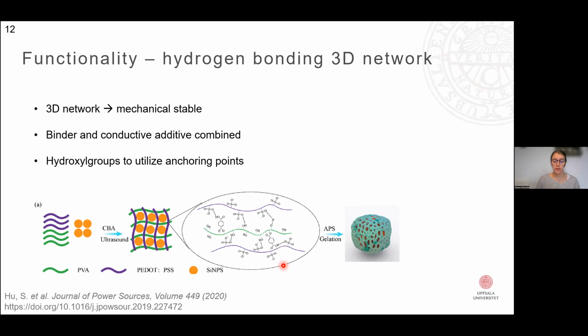Here's the difference. They also use hydrogen bonding, but in a 3D network, because they claim that it makes it more mechanically stable through the volume changes. So here they have a conductive self-healing hydrogel with a 3D network based on PEDOT:PSS coupled with PVA as the binder. And this network functions both as the binder and the conductive additive. And the authors mention here that conductive binders often have a more stable electron transport compared with the traditional conductive additives that we use, which tend to more easily lose contact with the silicon particles. And they also compare this with using only a conductive polymer as the binder, but they say that this will not cope with the volume changes of silicon on its own, but they need this 3D network for it to function.